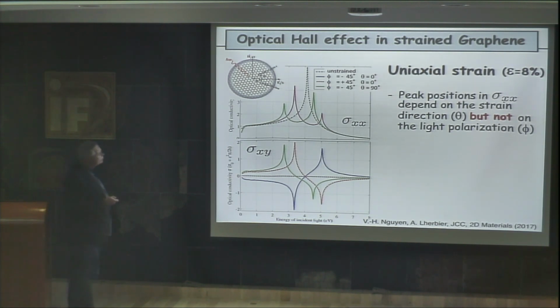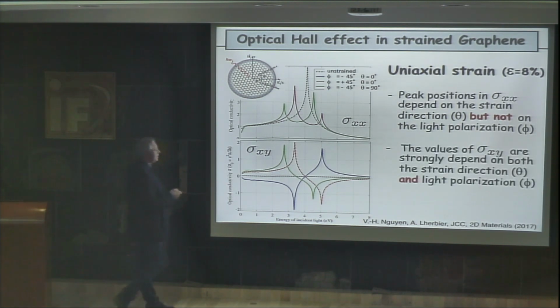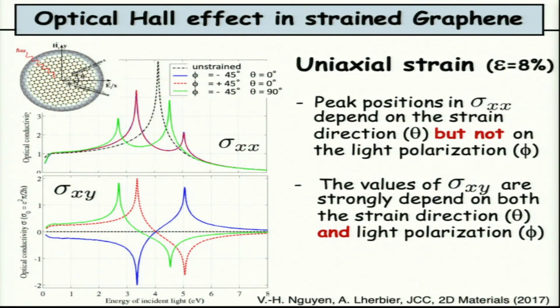Okay, so if we look more specifically, we have tried to modify the direction of the strain and the direction of the polarization of the light for a certain magnitude of strain, and you see that in fact the peak position in the optical conductivity depends directly on the direction of the strain, but not on the light polarization. So the blue and the red curve are exactly degenerate here. This is not the case for the optical Hall conductivity, which depends, as you can see, strongly on the direction of the strain, so theta, but also on the light polarization. So you see that when you change the value of phi from minus 45 to plus 45, you get completely two different curves, which is not the case here in the optical conductivity.